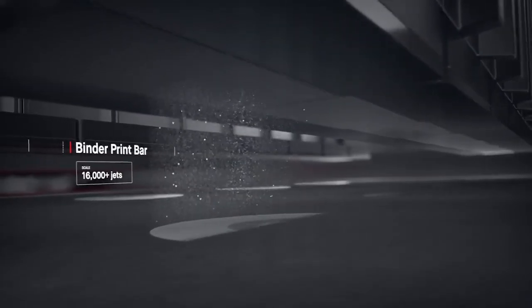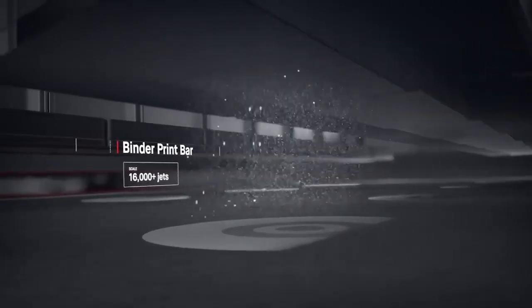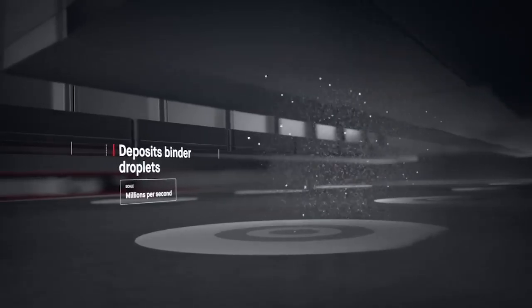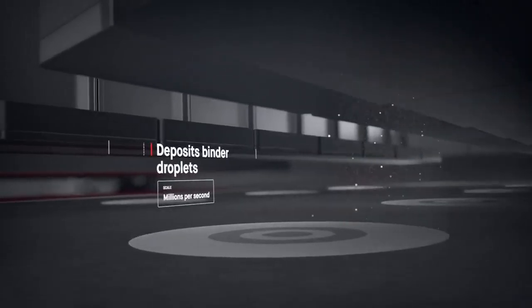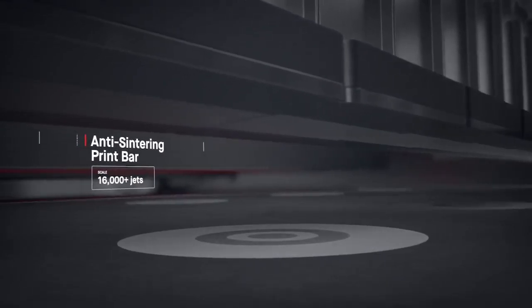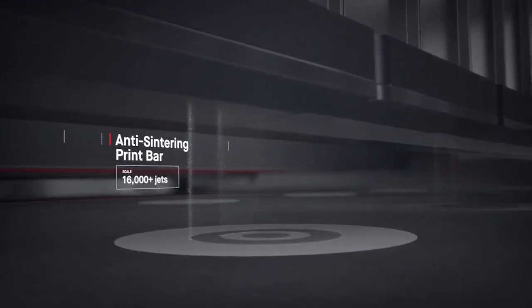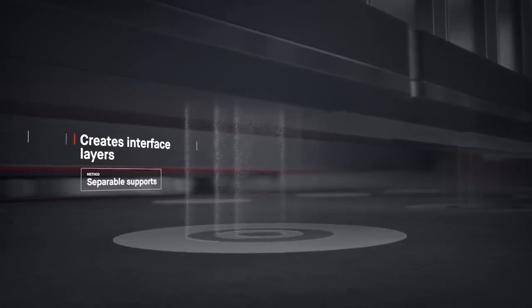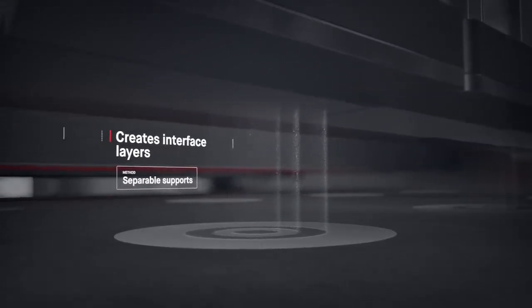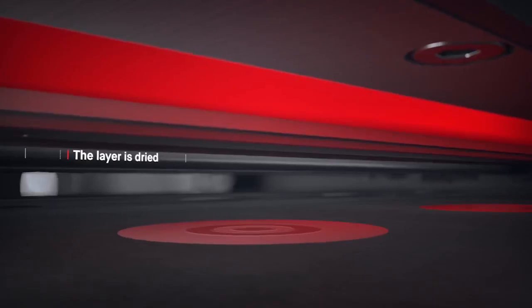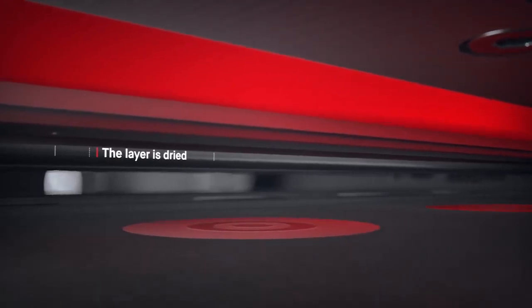The print bar follows, jetting droplets of a binding agent. Millions are jetted per second, binding metal powder to form high-resolution layers. Anti-sintering agents are then deposited, making it possible for supports to fall off after sintering, saving hours of post-processing. Once the layer is dried, the process repeats itself.